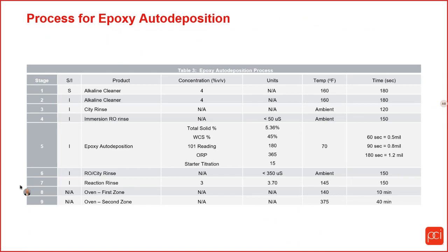So the process for the epoxy auto deposition that I followed, similar to what Steve said, goes through an alkaline cleaner. These were just standard panels. So it goes through an alkaline cleaner to clean any greases and soils that are on the panels. Goes through a couple of rinses, a city water rinse and an RO rinse. And then it goes through the epoxy auto deposition, which you can see on the right. Those were the times that it took to get those particular film builds.